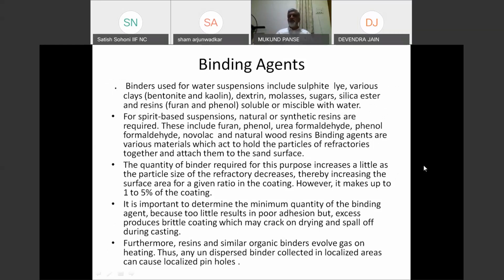For water suspension, the binding agents are sulfite lye, dextrine, bentonite, kaolin clays, or certain water-soluble resins. For spirit-based suspension, natural and synthetic resins, phenol, urea formaldehyde, novolac, and other wood resins are used. Binders act to hold the refractory particles together and attach them to the sand surface. The quantity of binder is again 1 to 5%.